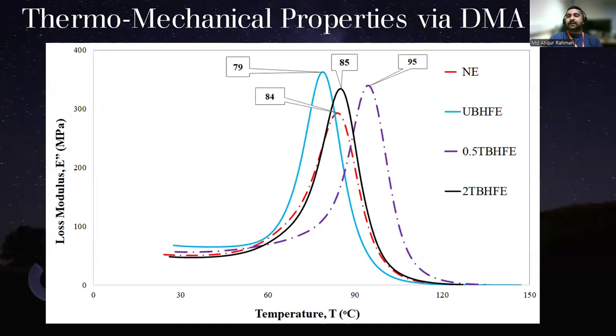Let's see the thermomechanical properties, the DMA. For this particular DMA, we of course use the industry standard, but there is a particular setting I still can remember: 10 hertz and 20 micrometer amplitude, and the heating rate was 3 degrees centigrade per minute. And the range is from room temperature to 150 degrees, depending on what type of resin we use. From that result, you can see that when I use the neat epoxy, the Tg, the glass transition value, is 84 degrees.